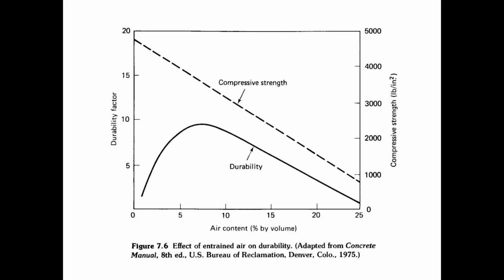Because I'm staying higher up on that compressive strength curve by limiting my air content to a maximum of 7, keeping it between 4 and 7. All right, so that's a very common specification for air content, 5.5% plus or minus 1.5%. So that means our allowable air range is 4 to 7. That's a very common specified requirement for air content. And this graph shows you why. It's because we're getting that peak in durability, but we're minimizing the amount of compressive strength loss.